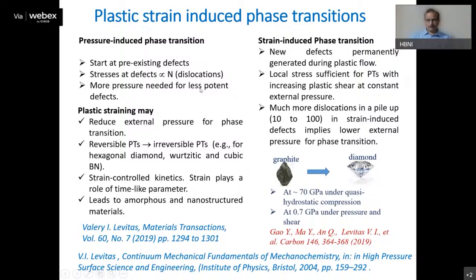So now when you introduce plastic straining to the system, for example, if you don't use any hydrostatic medium and you press the sample between the anvils and you introduce plastic straining, in that case, we permanently generate new defects. So now we are generating new nucleation sites. And at these nucleation sites, the dislocation pileups can be much higher than what we had in the case when we are studying the pressure-induced phase transition. So in principle, the transition pressure should reduce. The macroscopic transition pressure should reduce.